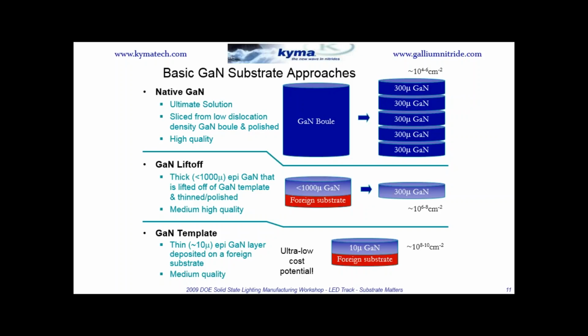But it leads to a wafer that has, and I don't have detailed characterization results here, lattice lensing, it's called, where if you did XRD across the wafer, you'd see the position is varying because the offcut of the surface is varying as you go across the wafer. It has to do with nuances of how this crystal growth starts when you initiate it, and it's an issue. So GaN substrates on the market have gotten cheaper and cheaper and more readily available, but I think the device people kind of hit a wall. They're not getting great yields, and so still people are primarily using foreign substrates for their devices.